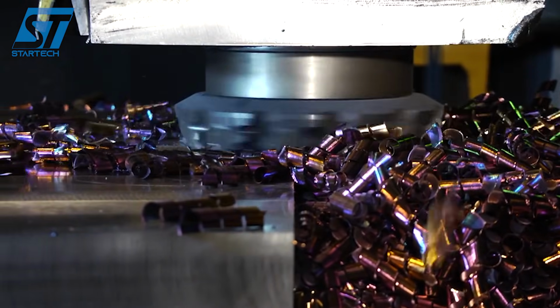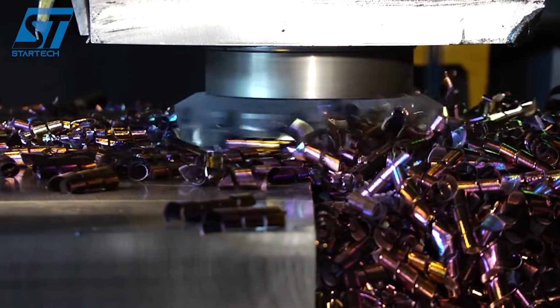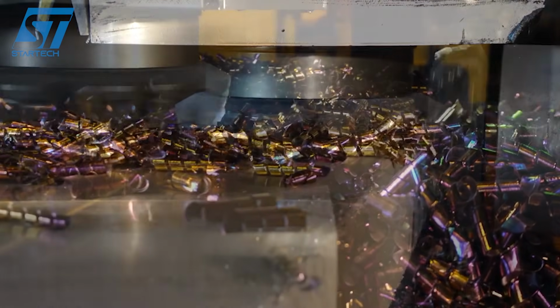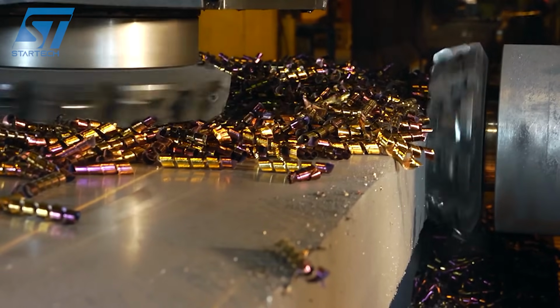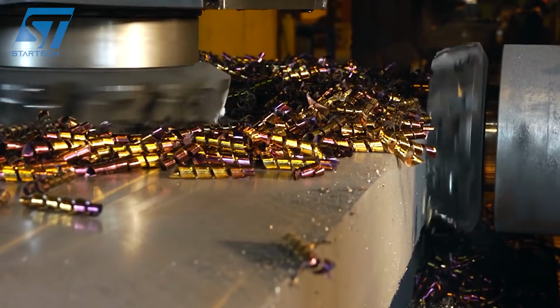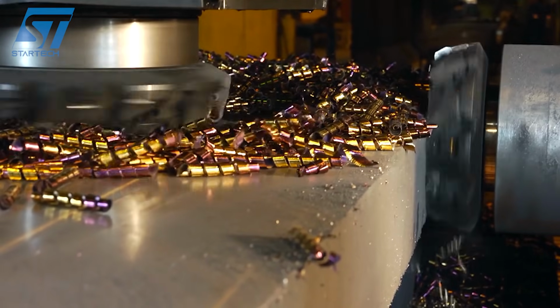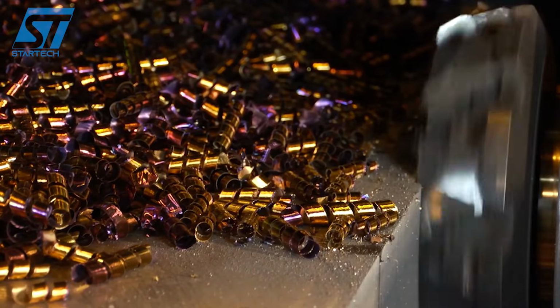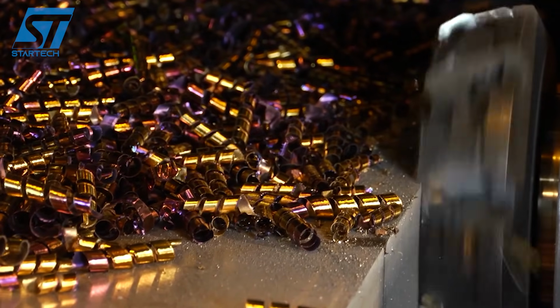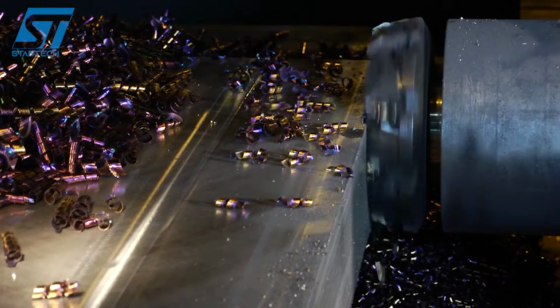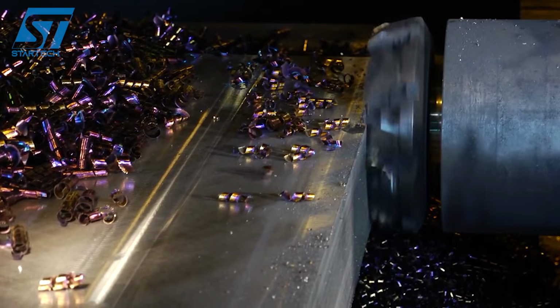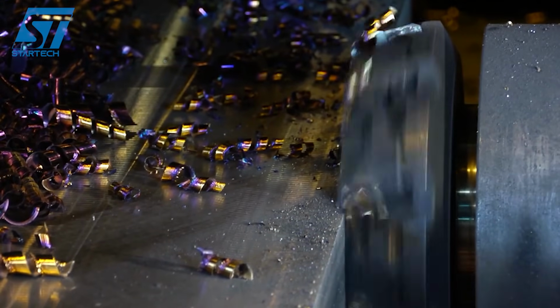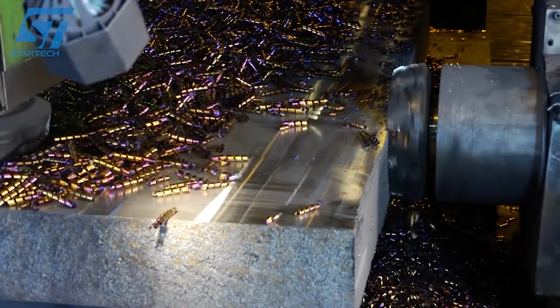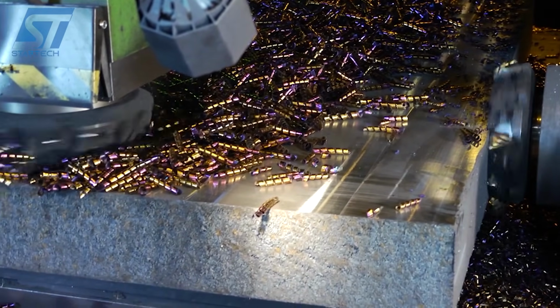The cutting tool you see there is a face mill loaded with carbide inserts, each insert engineered to withstand extreme heat and pressure. With each pass, the spindle removes layer after layer of metal with remarkable precision. We're talking about material removal rates that can exceed 50 cubic inches per minute on a roughing pass like this. What makes this kind of machining so impressive is the sheer rigidity required. The workpiece is clamped down with enormous force. The machine bed is built from cast iron or welded steel, sometimes weighing 50 to 100 tons, just to eliminate vibration. Because at this scale, even a tiny vibration means a flawed surface finish or a broken tool.